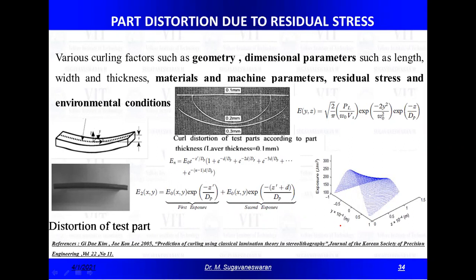For example, in this case, the exposure of UV light for a spot. So this is the spot size, that is Y. And with respect to depth, it gradually decreases. But within the cross section at the center, it is very high. It is because of a Gaussian profile, which we observe in UV light as well as in laser. So due to this variability and due to exposure of the laser to subsequent material, maybe we can have a support to overcome the issue.